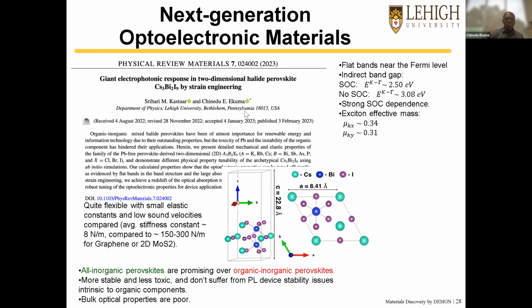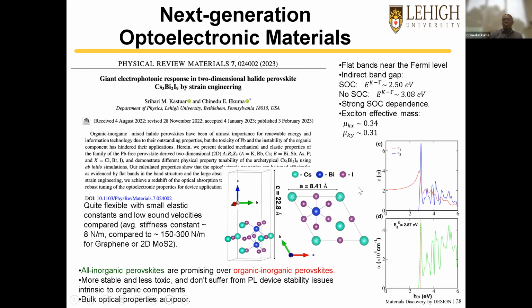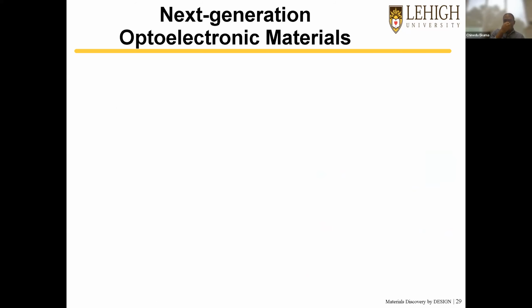What we saw in this material is that even though it is quite flexible, because of their small elastic constant, Young's modulus and the rest of them, compared to other 2D systems like MoS2 that have 150 or 300 newton per meter Young's modulus, this is like 8, so it's orders of magnitude smaller. So it's quite flexible, but it has a huge optoelectronic behavior, especially within the important EM, that is electromagnetic wave spectrum of visible light and near infrared, where photocatalysis and absorption are always of importance for photovoltaic or solar cell applications.